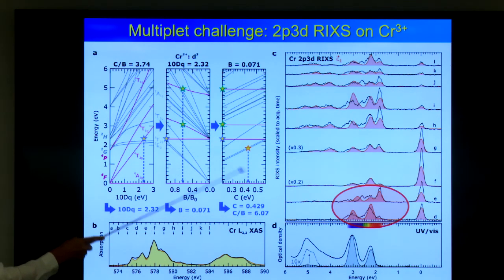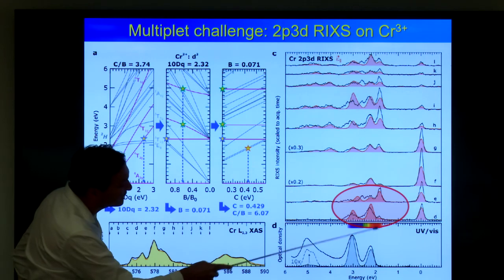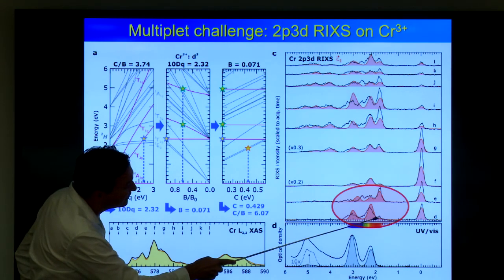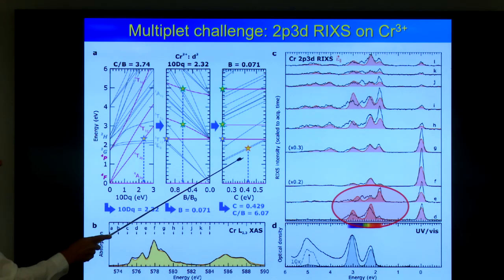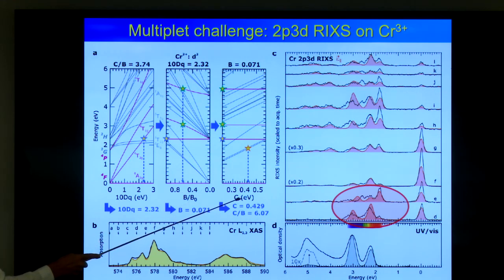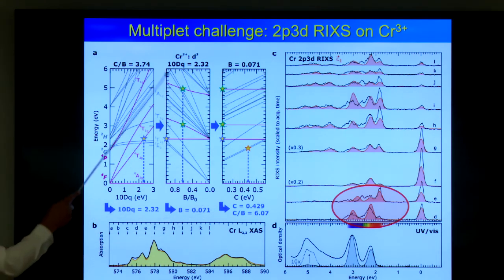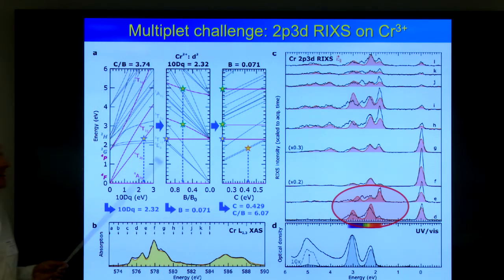And now from this spin-forbidden transition, which is there, you can fix the third Racah parameter C. So you get the 3 parameters determining the spectral shape in 3 digits directly from your RIXS spectrum. This would be completely impossible from X-ray absorption. So I call this a multiplet challenge because I give this challenge to the theoreticians to calculate from first principles.